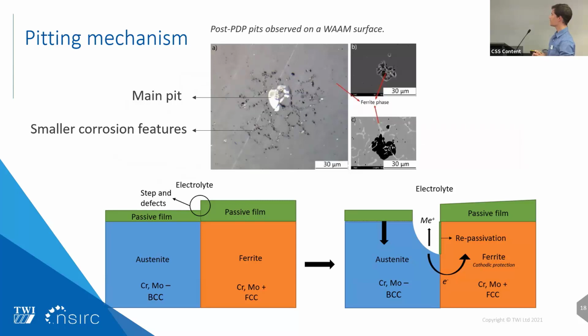Here we can see evidence of what is explained, where we have preferential dissolution of the austenite matrix, and here we have the ferrite phase, which remains fairly untouched. And this pit here, which is still in the early stage, you can see that it is initiating at the interface between the two phases.